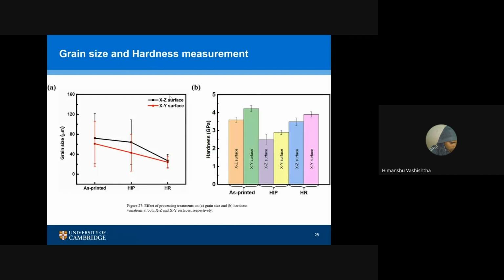Let's say even having the highest grain size reduction - overpassing 50% - for this hot isostatic pressing, the grain size was not that low, so it couldn't provide a pretty good high hardness. The dislocations also go away because you're heating it while applying pressure. So your defects are not there, and the grain size is also moderate, so that's why it shows the lowest hardness. However, it makes up some hardness because of the fine grain size.